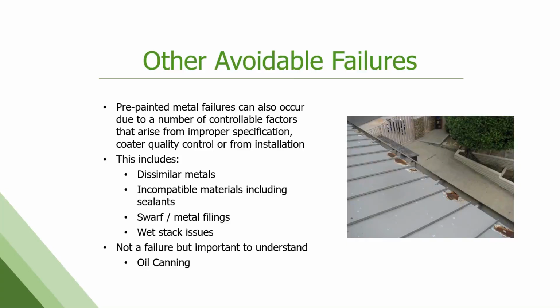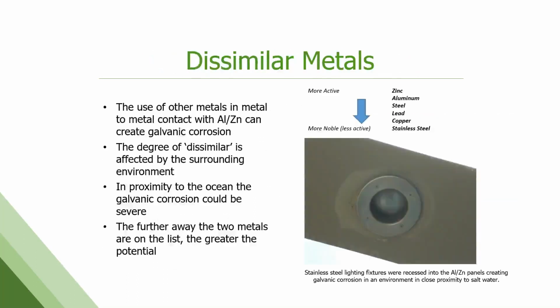So those are sort of the things that are covered in warranty, but there are other types of failures that occur that aren't necessarily a warrantable failure, but issues that we see out in the field that we need to be cautious of. And this would be dissimilar metals or incompatible materials being used with the pre-painted panels, Swarf or metal filings that are left and not cleaned up at the end of a job, and then storage corrosion. So either in coil form or the panel is being stored in a wet or hot environment before they go up on a building can lead to corrosion and issues. And then there's also oil canning, which is a shape issue that can occur.